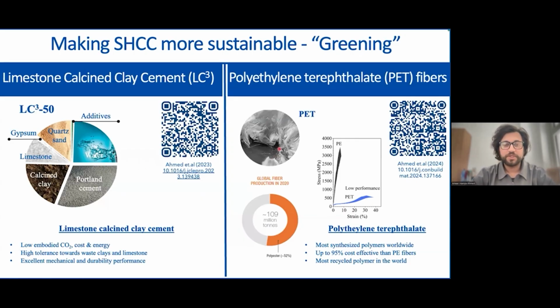On the fiber side of things, we can move away from the high-performance fibers such as PVA and PE, which you typically see in strain-hardening cementitious composites, and we can go for PET fibers. They are very attractive alternatives. They are very widely available, and they come from one of the most common polymer families in the world, which is polyester. Another advantage is that PET is also one of the most recyclable polymers around the globe. Apart from wide availability and recyclability, the cost of PET is really, really low. It's up to 95% more cost efficient than polyethylene fibers.